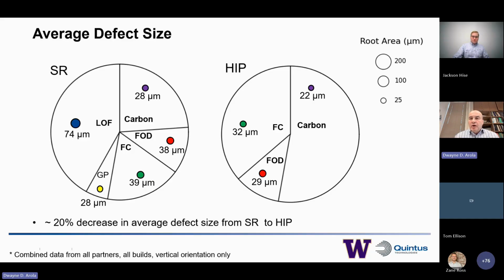But the thing I'd like to point out, which was really surprising to us actually, is that as evidenced on the fracture surface in terms of the Murakami dimension, we actually saw a decrease in the effective diameter of these defects. So we saw about a 20 to 25% decrease in the average defect size from the stress relief condition to the HIP condition. So we're still investigating what's contributed to that, what's actually the primary factor which is reducing the size of these anomalies that are contributing to fatigue response.